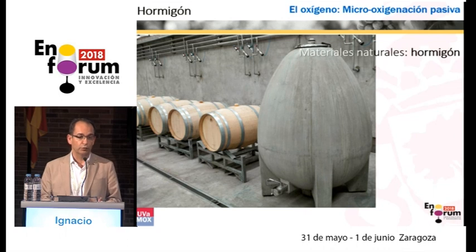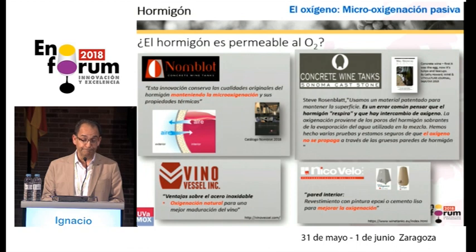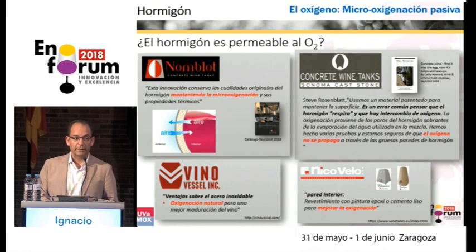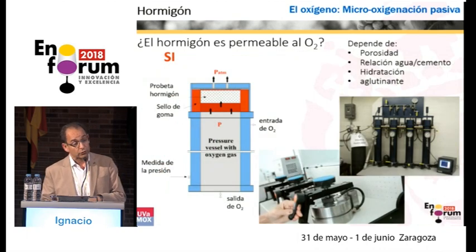Then we have concrete. We carried out tests at the university: we took different gauges and measured the dissolved oxygen at the top and bottom of the vat — this was with liquid, a real situation. In this case, there was hardly any absorption of liquid by the material, which is permeable to gases but not to liquids. The values were around 30 milligrams per year, which is acceptable for the profile we're looking at. So it is possible to produce with concrete and reproduce the values we like. We also worked on different dosings of those clays to achieve different permeabilities, simply managing the production technologically.